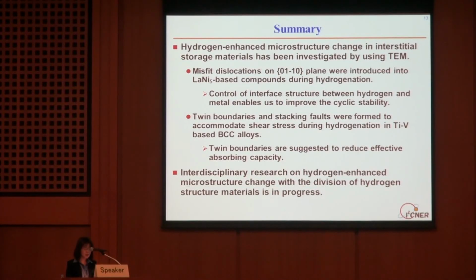In titanium vanadium-based BCC alloys, twin boundaries and stacking faults were formed to accommodate shear stress during hydrogenation. Twin boundaries are suggested to reduce effective absorbing capacity. Interdisciplinary research on hydrogen-enhanced microstructure change with the Division of Hydrogen Structure Materials is now in progress.